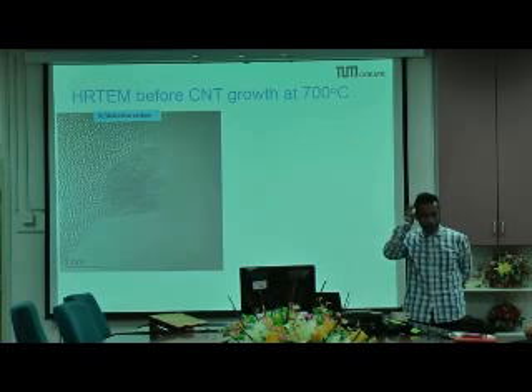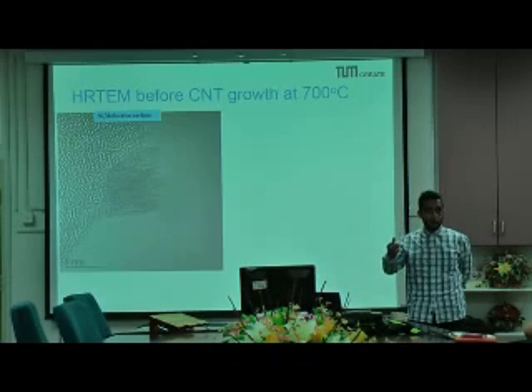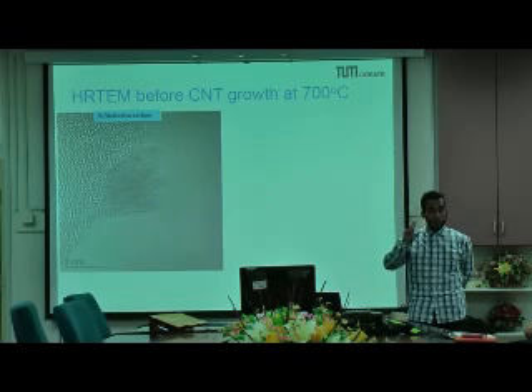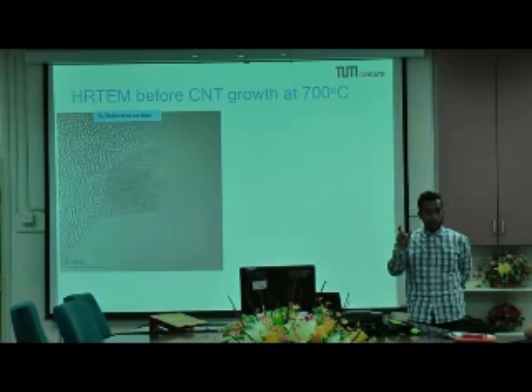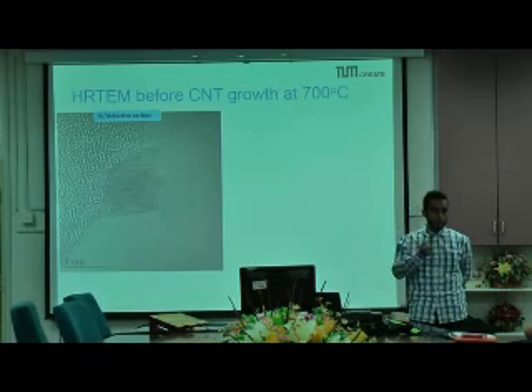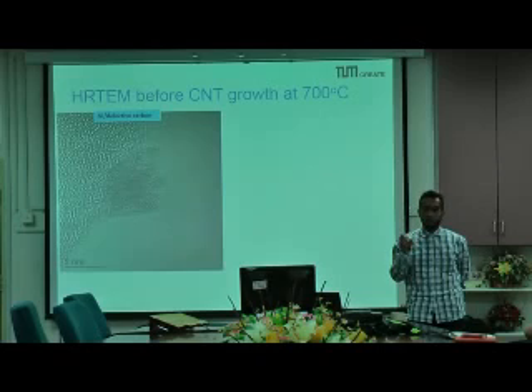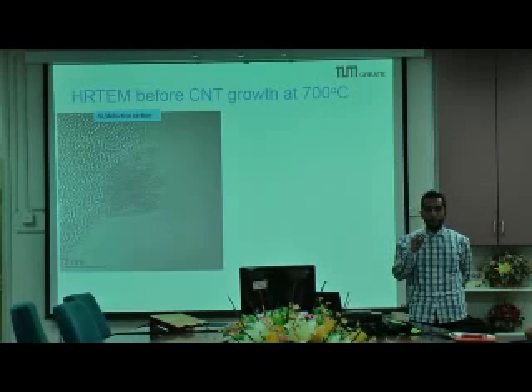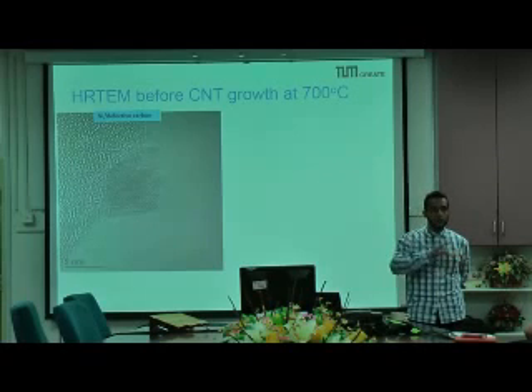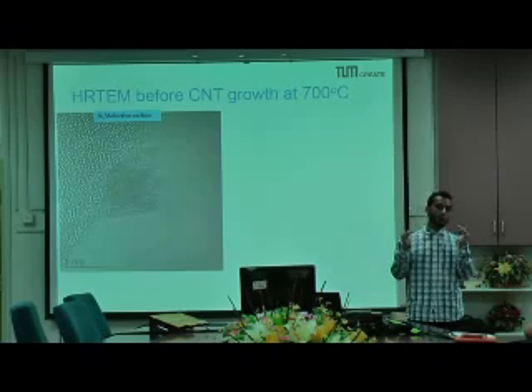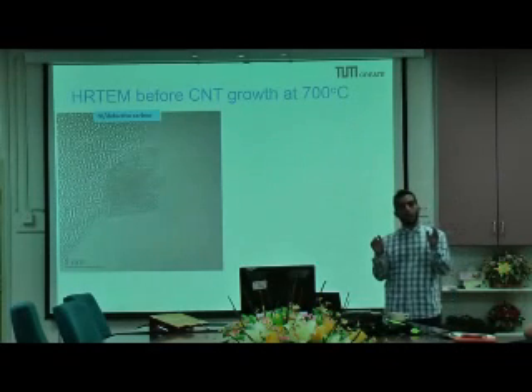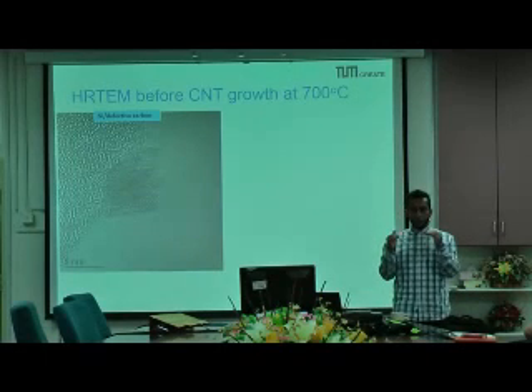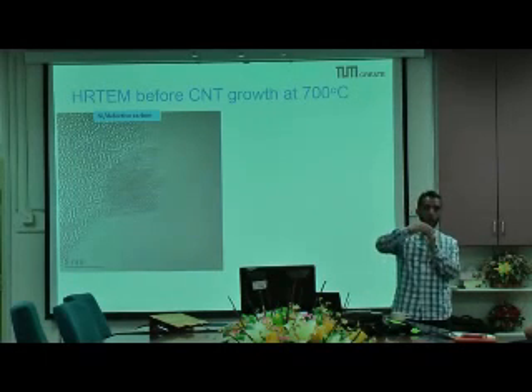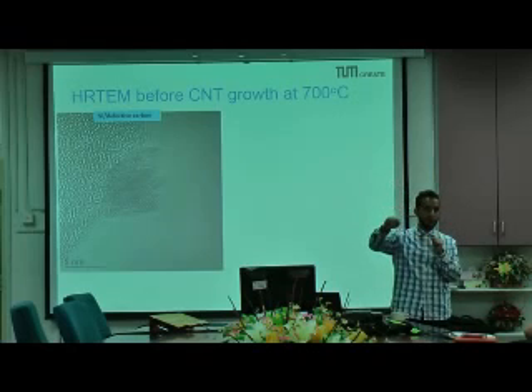So, the first part of the presentation, I wanted to highlight that if you have an effective carbon and an active material, the reaction between them is quite violent, and the carbon is extracted from the surface and goes to the bulk of the catalyst. When this happens, the crystal orientation in the bulk, as you have seen with TEM, changes. There are still reports in graphene synthesis that you need to have a registry between the 002 plane for graphene and the crystal. If you don't have a registry, if the crystal is just so messed up, then you don't manage to grow very nice graphene layers.